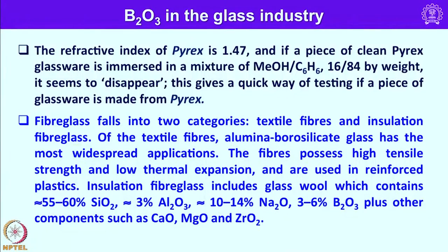The refractive index of Pyrex is 1.47, and if a piece of clean Pyrex glassware is immersed in a mixture of methanol and benzene in 16 to 84 weight ratio, it seems to disappear. This gives a quick way of testing if a piece of glassware is made from Pyrex or not. You should remember that one.